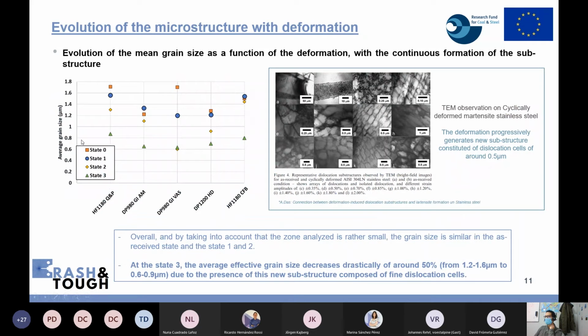So here we have the average grain size as a function of the deformation for the 4 states. And what we can see is that on average, when the crack propagates, the average size decreases, and this is due to the presence of the substructure. At the stage 3, the average effective grain size decreased drastically, by 2 times. So this is a real evolution. And we have seen in the literature that this kind of substructure was already observed by TEM, and that the dislocation cells were around 0.5 micrometers, close to what we have seen.